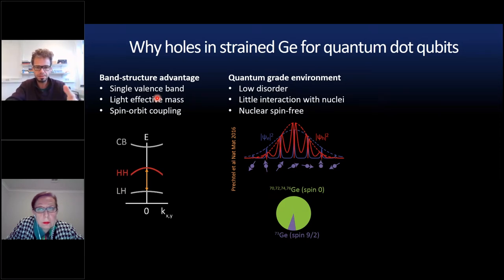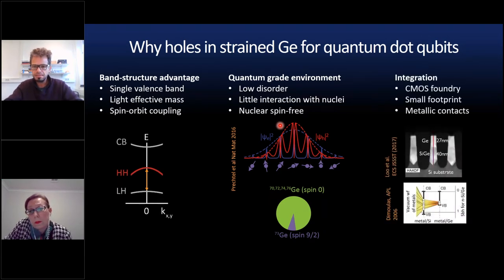Germanium is a great material to achieve a high quality, quantum grade, we call it, environment, where there is low disorder and little interaction with nuclear spins. And furthermore, germanium can be purified into a nuclear spin-free material. And these interactions with the nuclear spins are the main cause for decoherence. Finally, germanium can be integrated into a CMOS foundry.